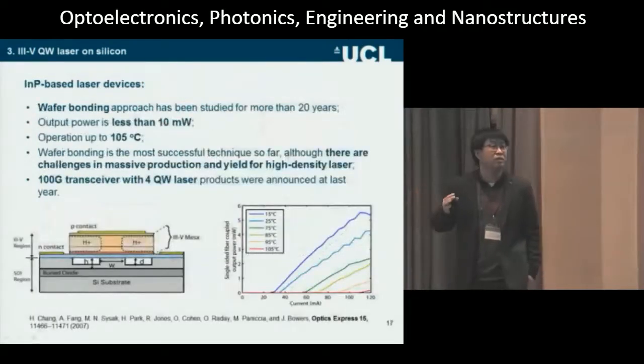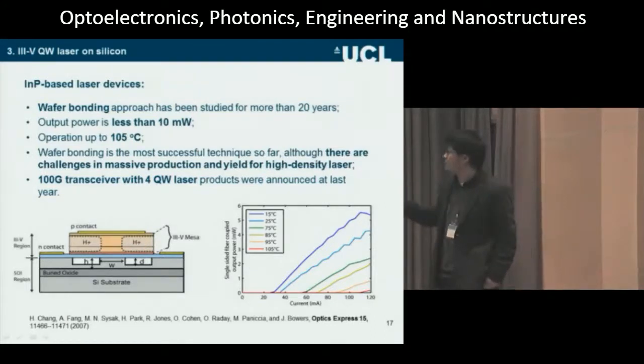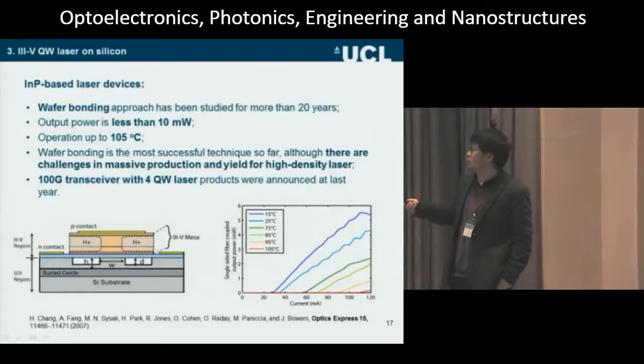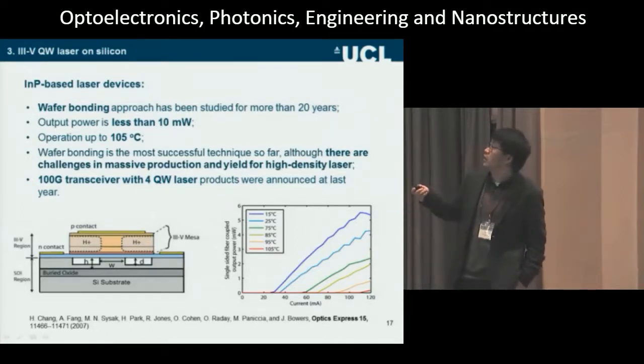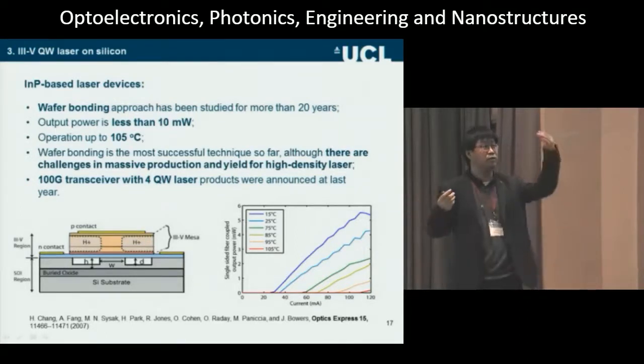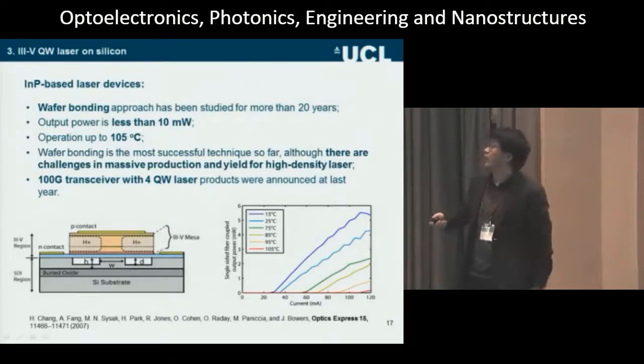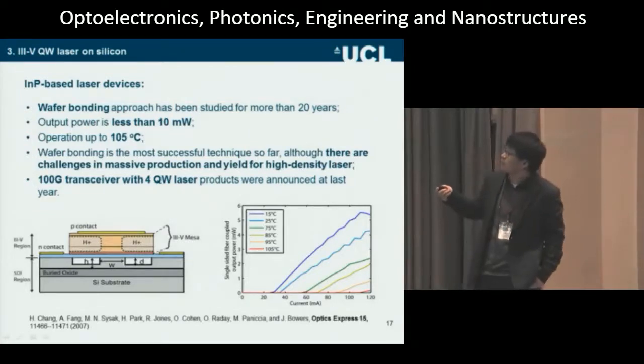Because monolithic growth doesn't work for quantum wells, another idea came out from Europe and the US. I'll give you one example from UCSB, Santa Barbara. They collaborate with Intel. So that's their best result. This uses wafer bonding. You just grow the III-V materials, bond them on silicon, and you get the device working.